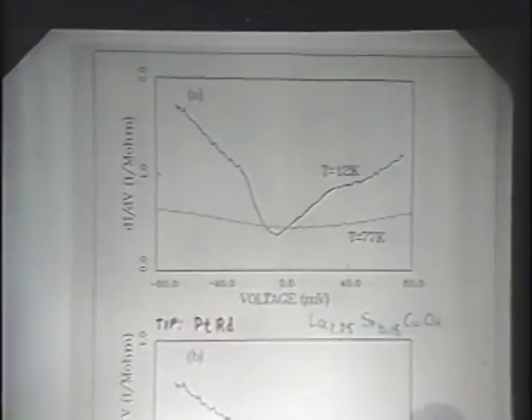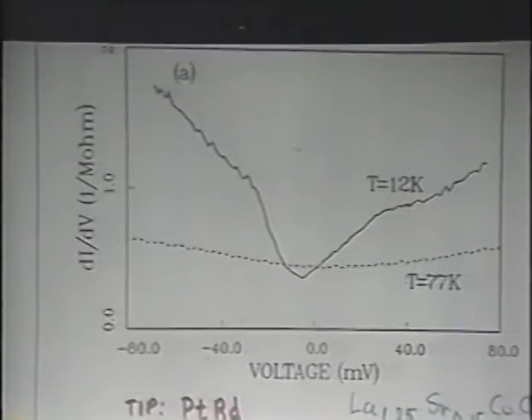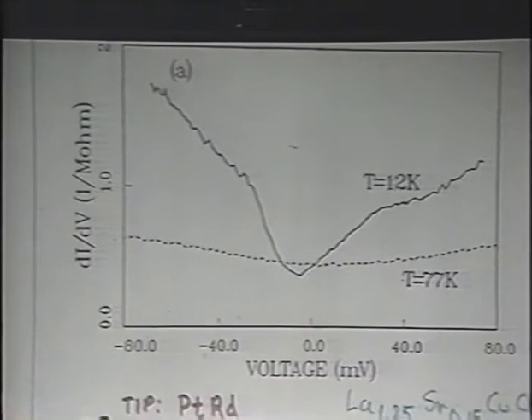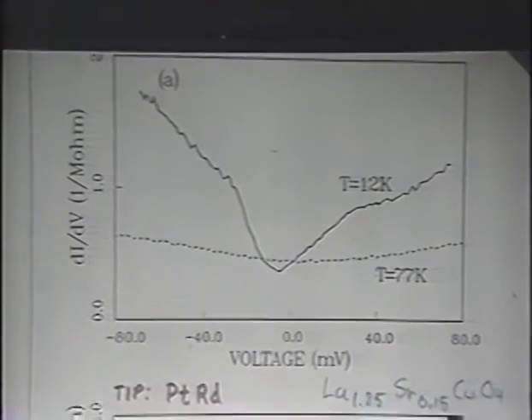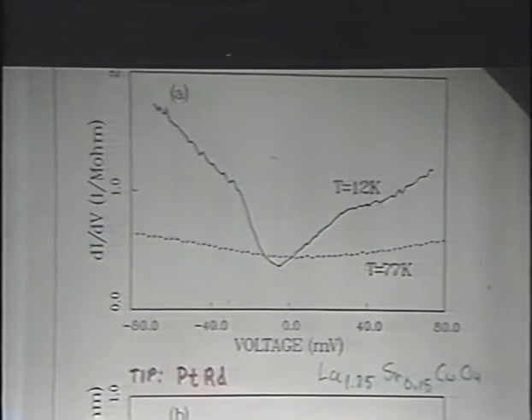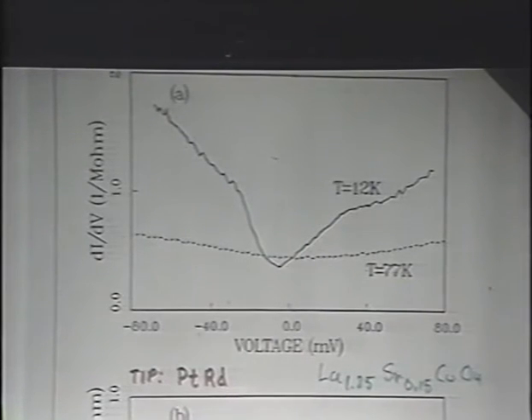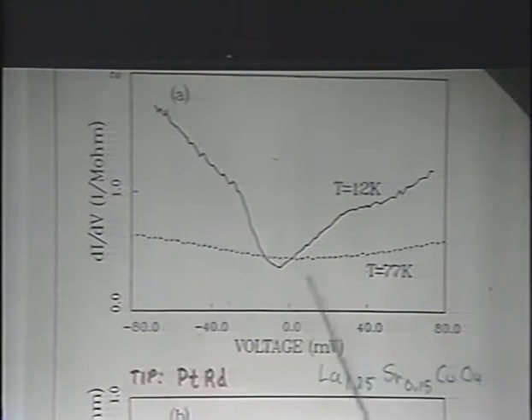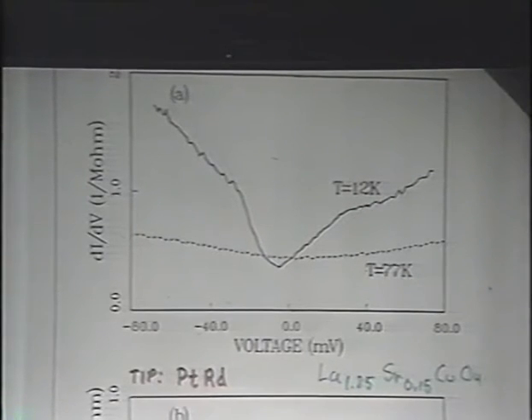If we let the computer do the work and average IV curves, then much better data is obtained, much smoother. And I should point out that the curve shown here at 77 Kelvin is very characteristic of the material. In this case, we had to dig into the surface of the material because it was as received. Namely, the surface had some crud on it, perhaps some semiconducting or insulating material on the surface. Basically, we never saw a structure like this at 77 Kelvin. So that is a good pointer that gap there is probably due to superconductivity.